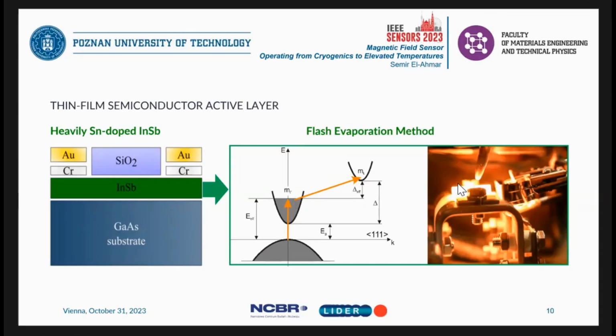It's heavily donor-doped indium-antimonide. We use tin as a donor because we want to improve the thermal stability of the thin film. Normally, indium-antimonide is a narrow bandgap semiconductor, which is not optimal for fabrication of thermally stable devices. However, using appropriate and precise doping, we can make the Hall coefficient almost independent of the temperature in some temperature range, which makes the signal of the sensor also quite independent of the temperature. Of course, it's not fully independent of the temperature, which we will see.